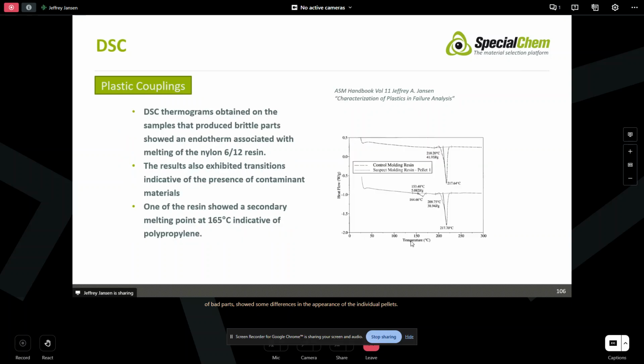The control molding resin that we had from our retained, again, looks like a nylon 612, melting point around 218 degrees C. One of the discrepant pellets looked a little different, had that same melting point, but also had a melting point about 165. Again, tells us that that's likely contaminated with polypropylene. So we've got non-homogeneous pellets.